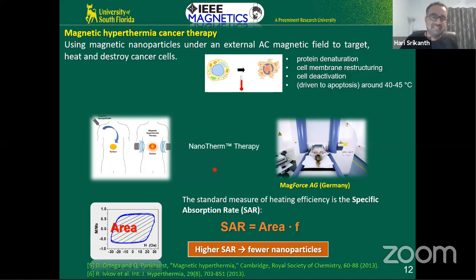So essentially, this is the AC hysteresis. And the way to understand this is that when you apply a high frequency, large magnetic amplitude signal, essentially the particle is saturating. And then in the other cycle, it's saturating on the other side. And when it's fast enough, the large magnetic moment of these nanoparticles, think of each particle as a super spin, is unable to follow the high frequency, so it goes out of phase. And because of that, you have this hysteresis loop. We want to maximize it. We want to maximize the area.